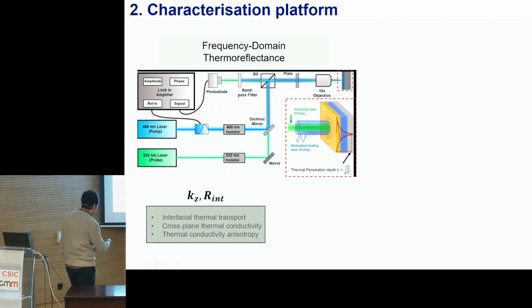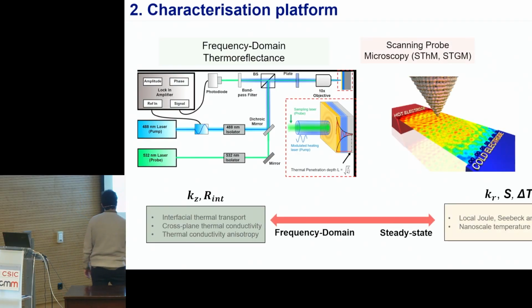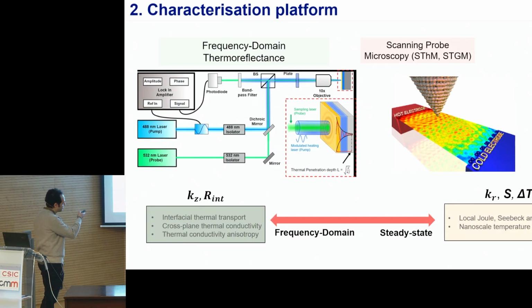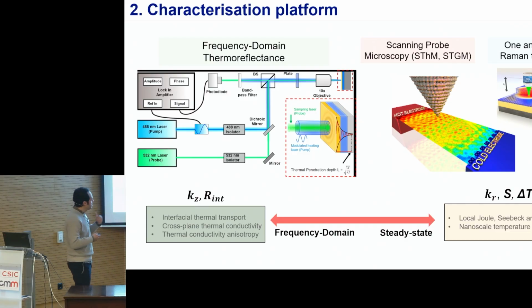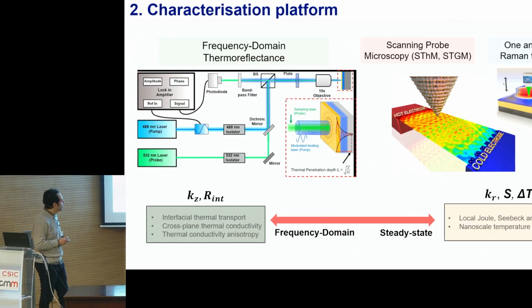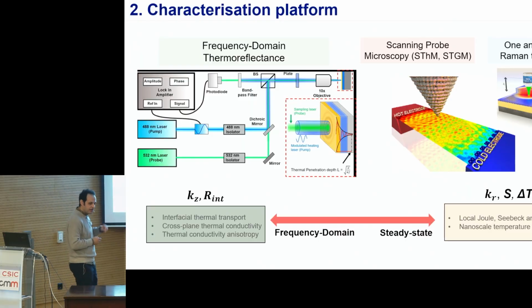Then the second is the scanning probe microscopy. Here, let's see if we have time, I would like to show you two different modes of this scanning probe microscopy, the scanning thermal microscopy and scanning thermal gate microscopy, where we can really probe thermal and thermoelectric transport in active devices, and we can see the temperature mapping in active devices. And then we have the 1 and 2 laser Raman thermometry, that I used to use during my postdoc time in ICN2, and we still have collaboration, and we are still using this technique.